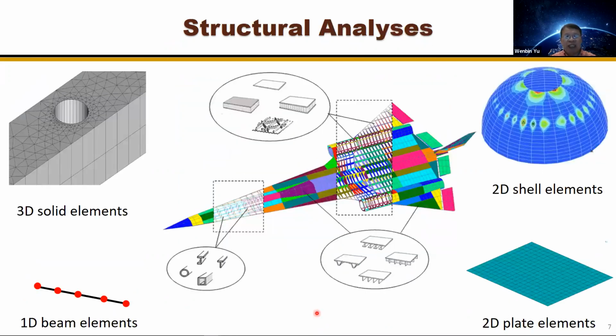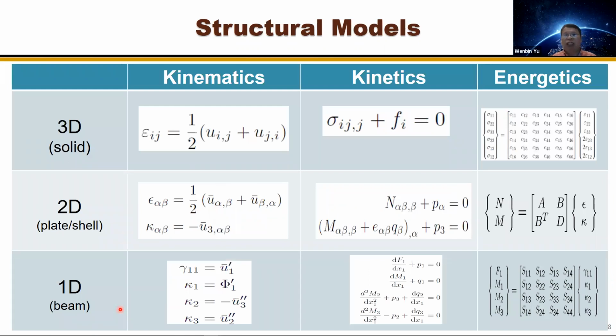And when we do the analysis and design, we discretize them as a combination of solid elements, plate and shell elements, and beam elements. And what we have to realize is that this single-segment line element could represent a box beam with each wall made of, say, 20 layers of woven fabric. And this 2-dimensional plate surface element here could be a stiffened panel with skins and stiffeners made of composites. And what we need to find out is how we can capture the behavior using this much simplified mathematical representation. And that is what we call the models. Behind each element, there is a corresponding model.